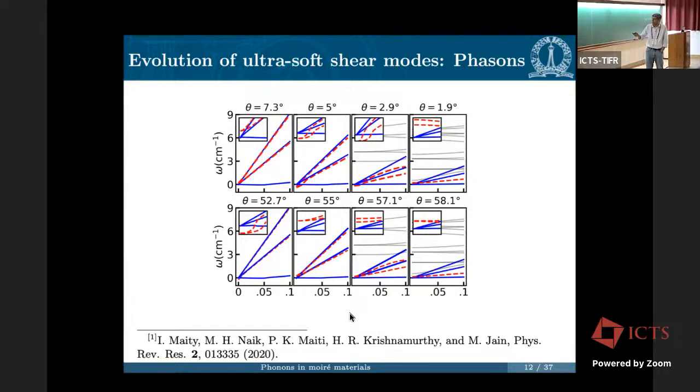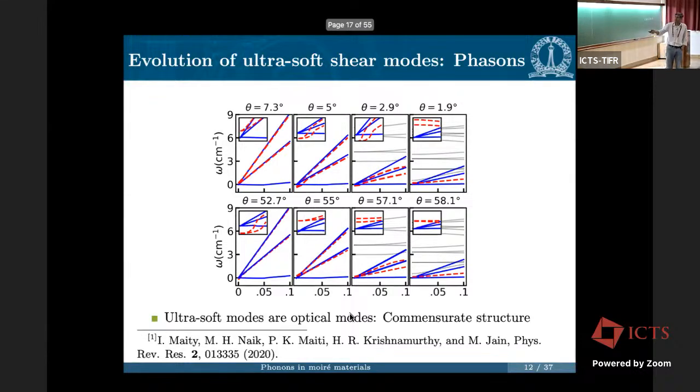But by and large, you're seeing all the acoustic modes, and then you see suddenly these modes, and they turn around right at the end. So they are gapped out, but they're gapped out at 0.2 centimeter inverse or of that order, which essentially is zero for all practical purposes. Yeah. They are Goldstone modes. There are indeed Goldstone modes. And I'll explain in just a minute.